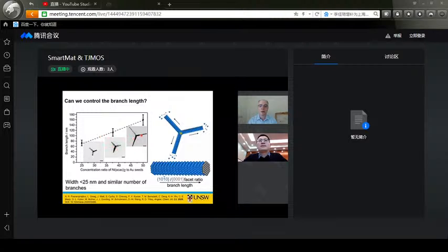As we're growing longer arms, we were essentially changing the ratio of these side facets compared to how many nickel atoms are on the end facet. And actually, it's this side facet that's the more active. So this is the kind of shape that you're after, with the longer arms rather than shorter arms, for a better catalyst in this process. So yeah, the shape can really control the catalytic properties tremendously.